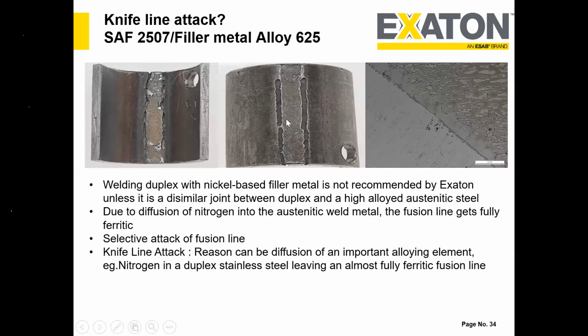This is very important. Why should we not weld super duplex with Inconel 625 or ENiCrMo3? The welding of duplex stainless steel with a nickel-based filler wire is not recommended unless it is a dissimilar joint between duplex and high-alloyed austenitic stainless steel. Due to diffusion of nitrogen into the austenitic weld metal, the fusion line gets fully ferritic, which is dangerous. It has a potential for selective attack on the fusion line, and also a potential for knife line attack. The reason can be diffusion of important alloying elements, that is nitrogen, out of the duplex stainless steel, leaving an almost fully ferritic fusion line.